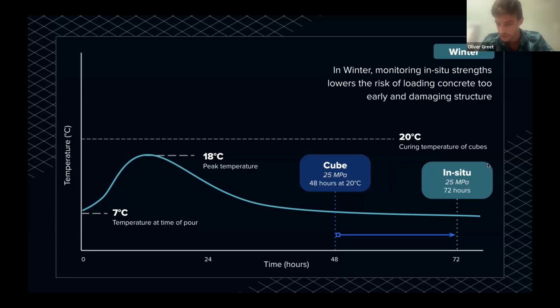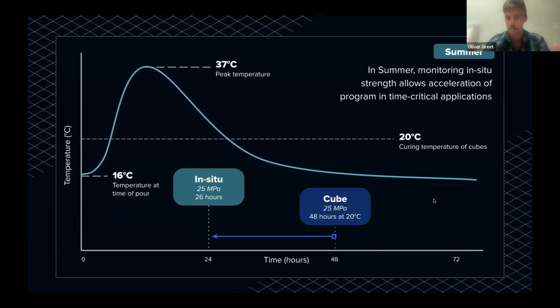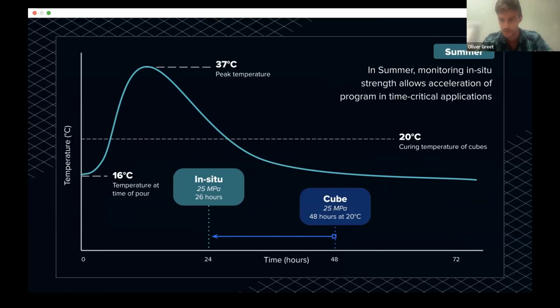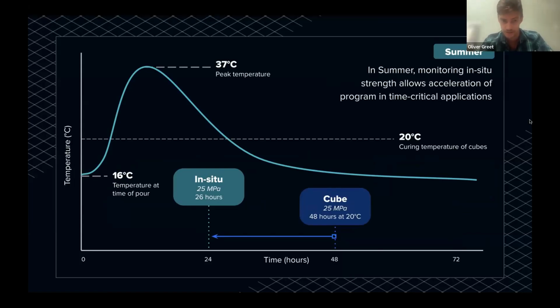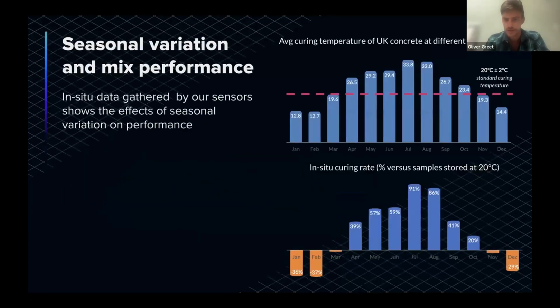The in situ concrete, which is slightly cooler, is going to take longer, and as a result, that's going to take 72 hours. So this gives you an understanding of the summer and winter cases and the merits of using sensor-based monitoring to track the strength gain in each condition. Ultimately, the cubes themselves are going to give a slightly incorrect picture of how the concrete is gaining strength, and that's particularly relevant in these first 24, 48, 72 hours, while we see a lot of that thermal activity from the concrete itself.